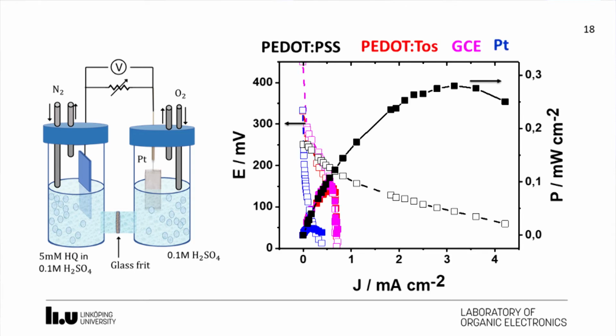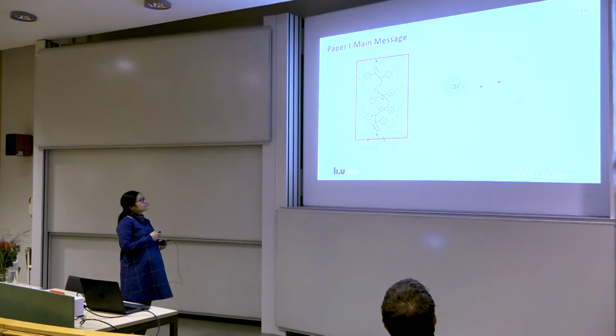The results show that on the PEDOT:PSS electrode, we observed the smallest voltage loss, and it also yields the highest maximum power, followed by the PEDOT:TOS electrode, the glassy carbon electrode, and the least on the platinum electrode. The result from the device level is in good agreement with the initial electrochemical studies.